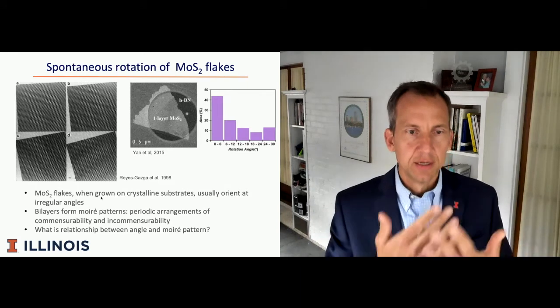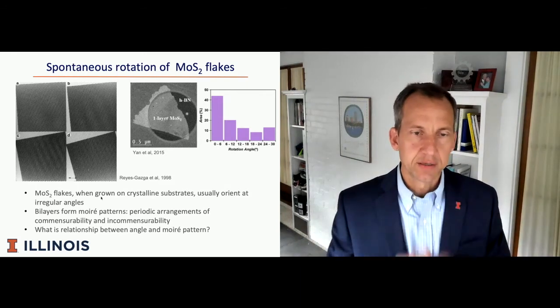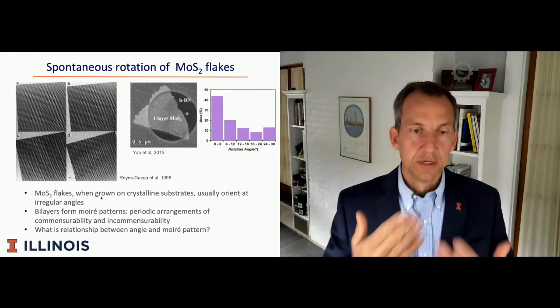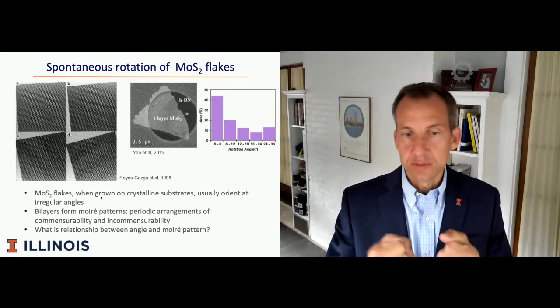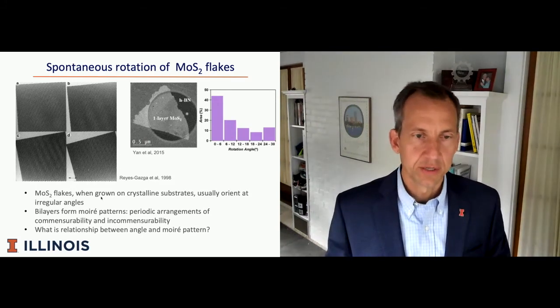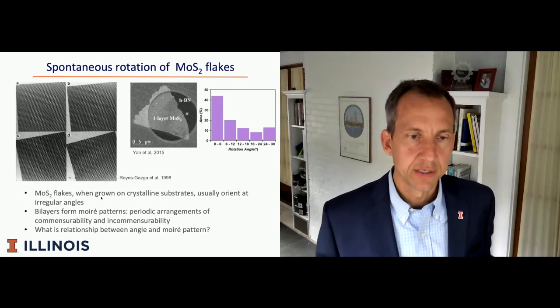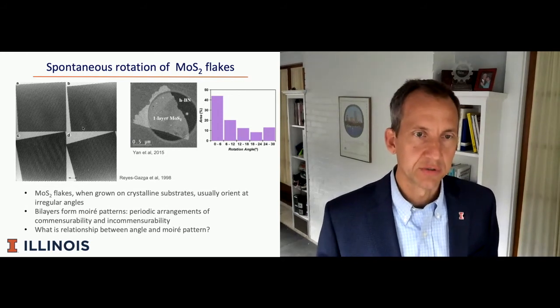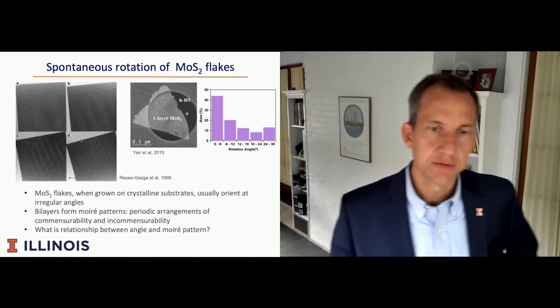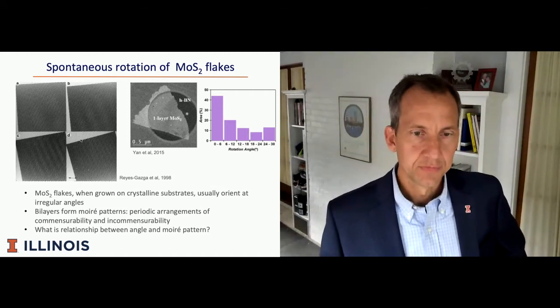Anytime we see two layers that have periodic structure offset from one another, or strained or twisted relative to one another, we see these interference patterns, these superlattice patterns. And that's what's observed in this 1998 high-res TEM study of bilayer MoS2.